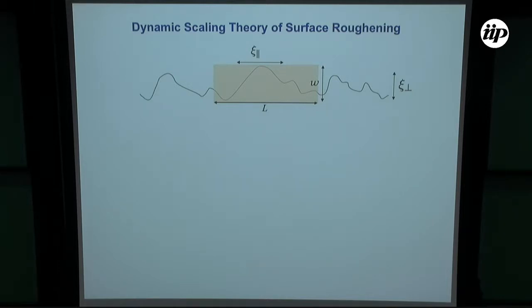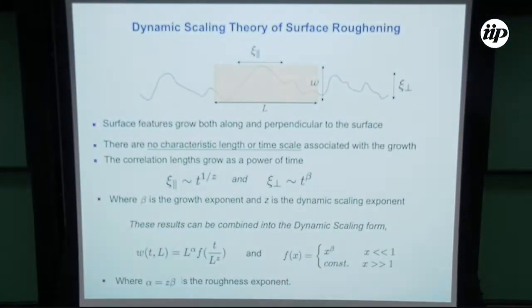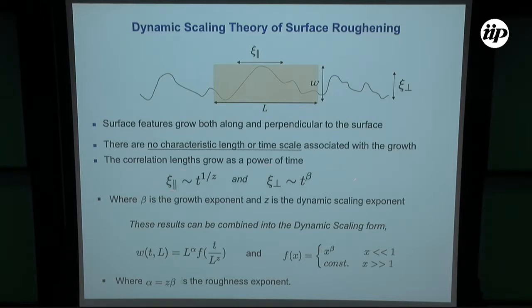So the dynamic scaling idea is the following. It's very simple. It says, look, these two are generally independent and depend on the dynamics of the system. But there is no characteristic time or scale that characterizes them, so that we would expect, going back again to the idea of critical phenomena that David was talking about, we would expect these correlations to grow as power laws. The reason these exponents are denoted strangely is historical, but think of this just as one exponent and beta as another exponent. Beta characterizes what I've been emphasizing, the fact that the roughness grows with time. So beta characterizes the growth of the surface roughness with time, and this 1 over z characterizes how features on the surface spread along the surface.